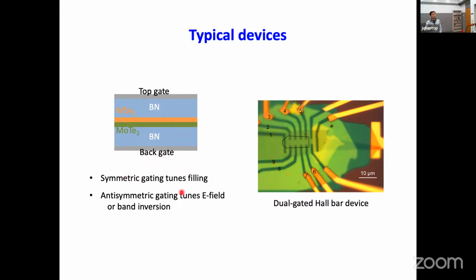We can independently tune the total filling factor, or the total electron density within this heterobilayer. Or we can just apply a vertical electric field without changing the doping density in the bilayer, and that tunes the band inversion and the band structure in the heterobilayer. And we also put multiple electrodes into this heterobilayer structure to form a Hall bar device, for instance, shown here.